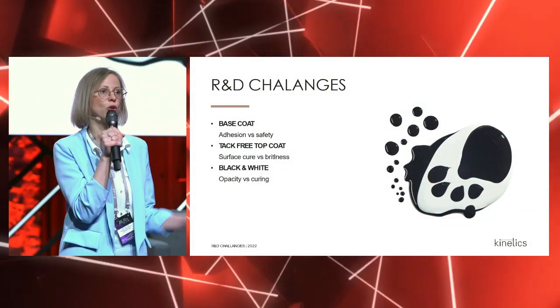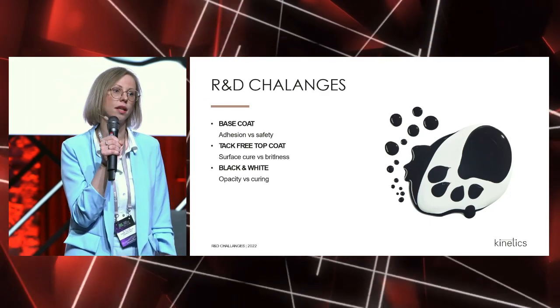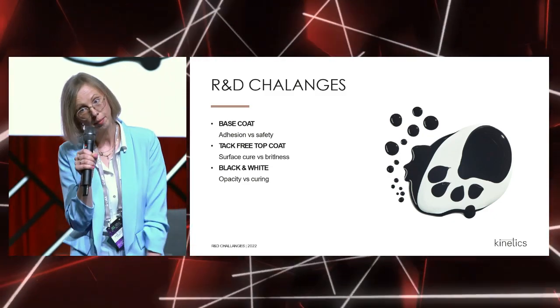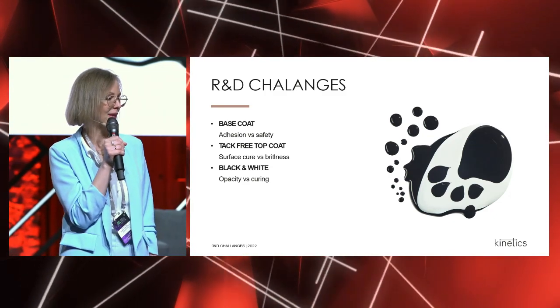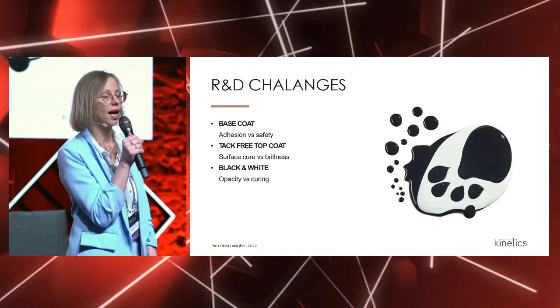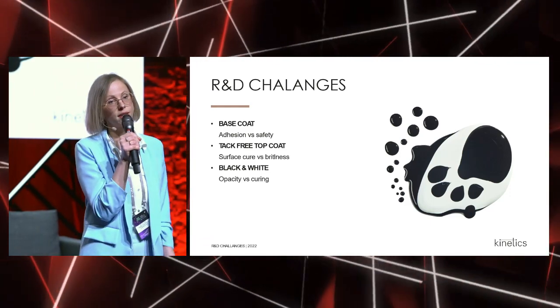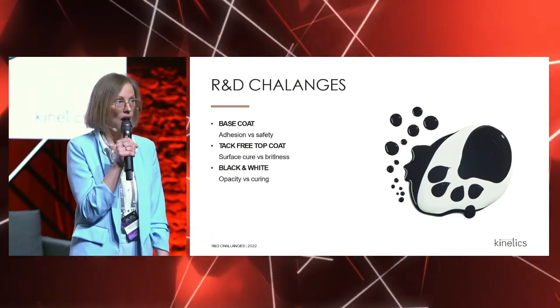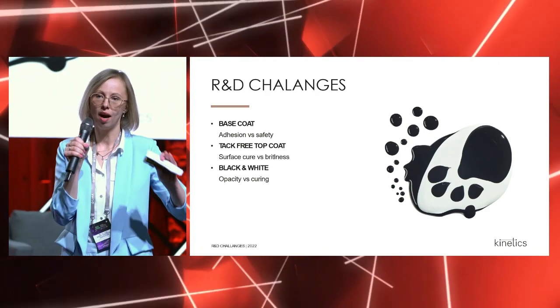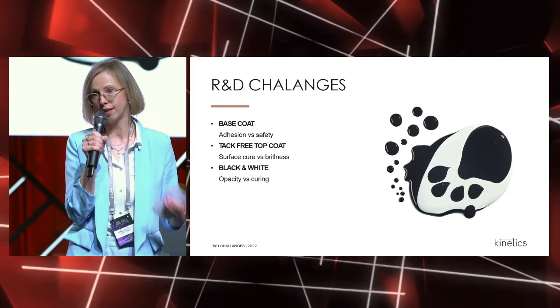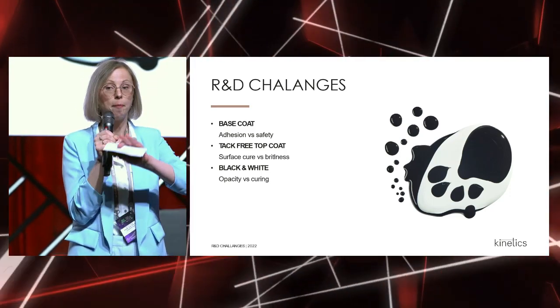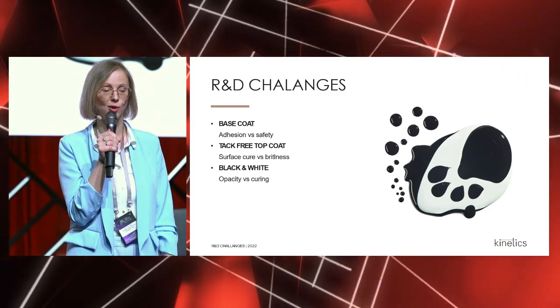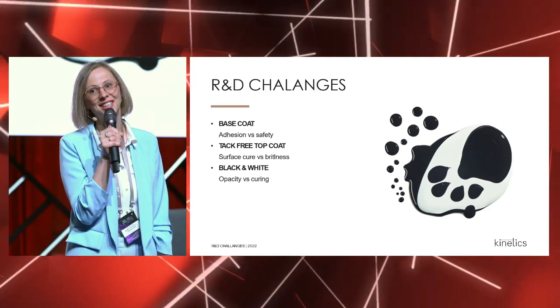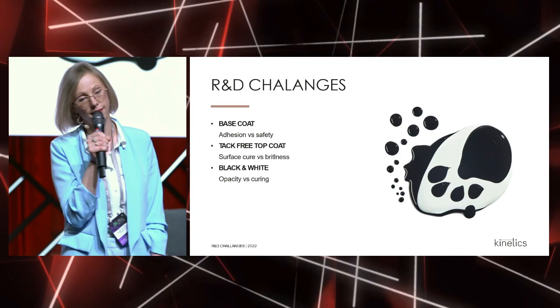The challenge my R&D colleagues face is the adhesion of base coat, adhesion and safety. Because to have great adhesion, we can use harsh chemicals, but not on natural nails. And therefore, we should use mild chemicals and still somehow get good adhesion. There is one more challenge. We would like to make the coating without a tacky layer. Because in the industry now, the upper part of the coating connects with oxygen, and the oxygen inhibition layer appears in the upper layer. But we would like to avoid oxygen somehow, and to make the coating without this tacky layer.